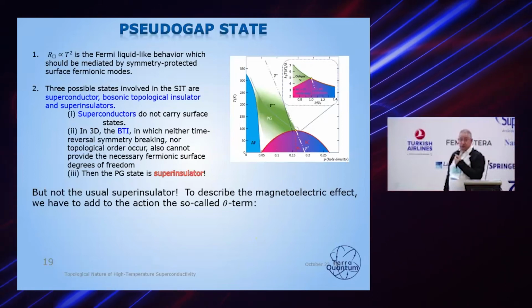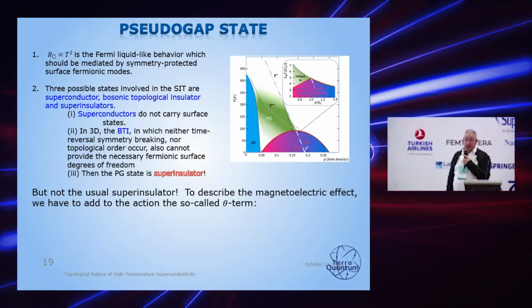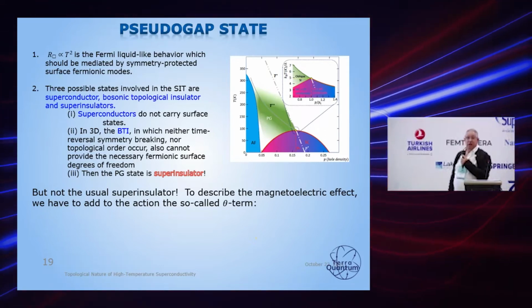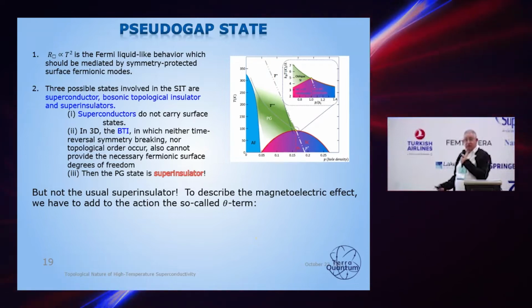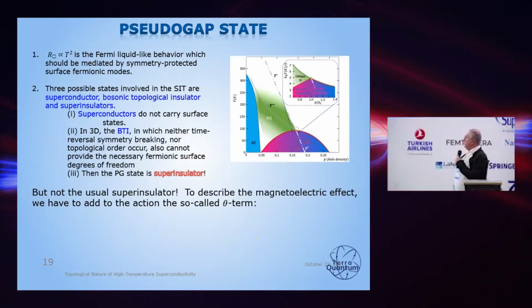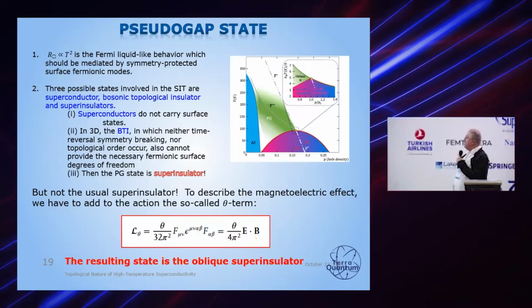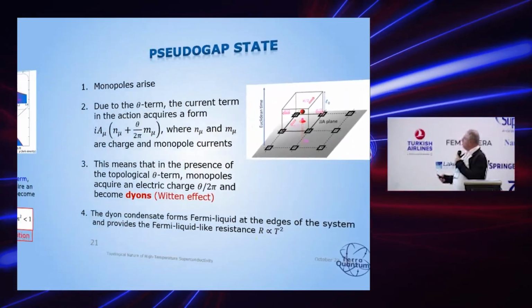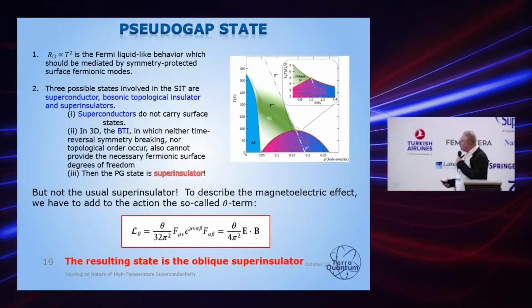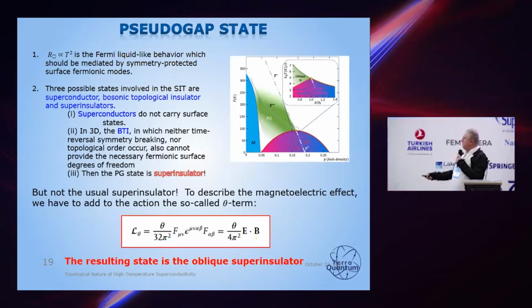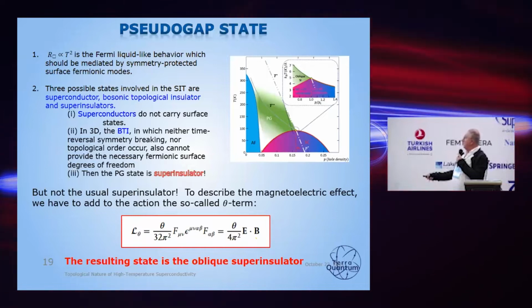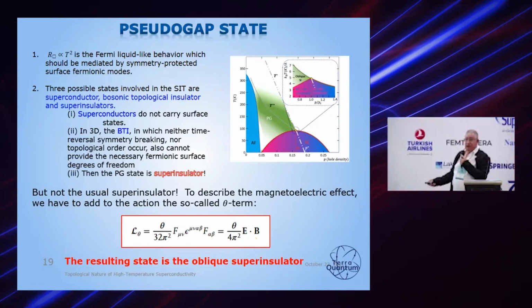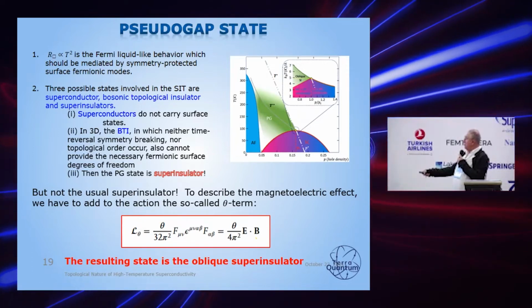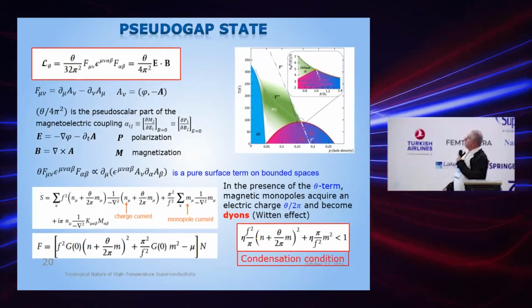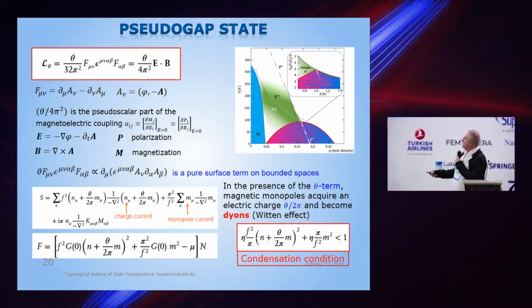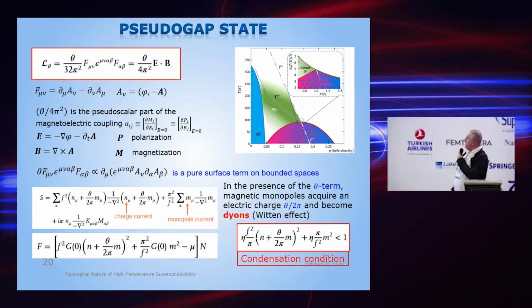But this is a superinsulating state with one small subtlety. It's not the usual superinsulator. This is a superinsulator which demonstrates the magnetoelectric effect, which is not explained, I remind you. How can we describe the magnetoelectric effect? Well, again, we will make a textbook move, and we add what is called the theta term, which looks like that. Okay. So this is the well-known magnetoelectric theta term, and the resulting state we can call an oblique superinsulator. And you can see that this comes from this polarization term. And this indeed describes the magnetoelectric effect.